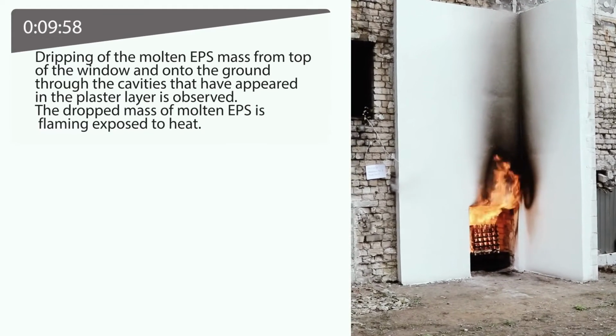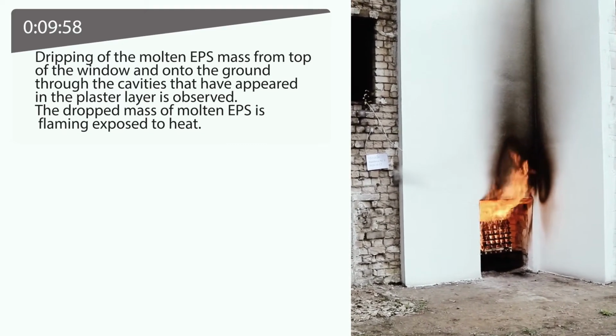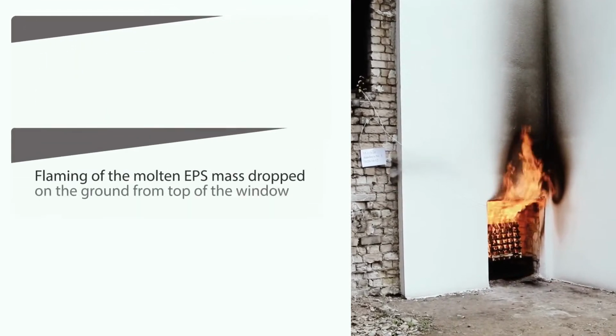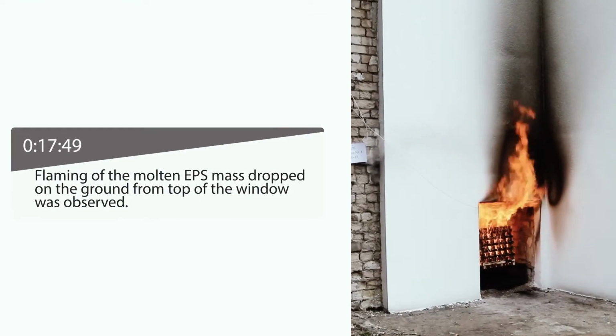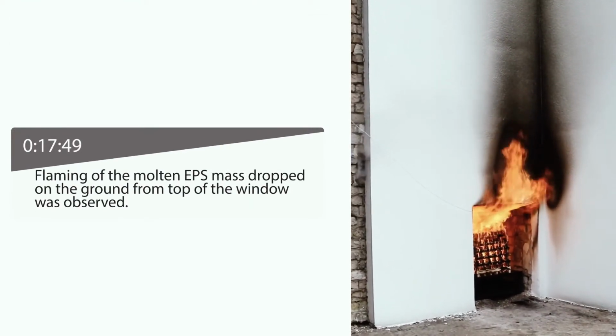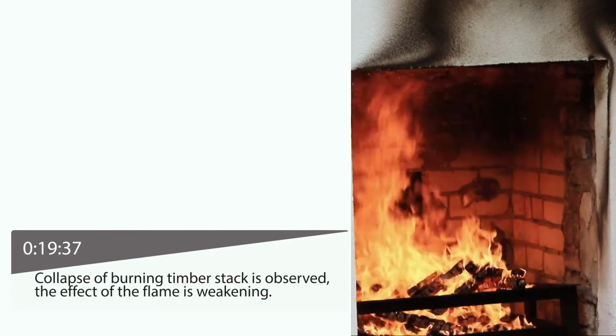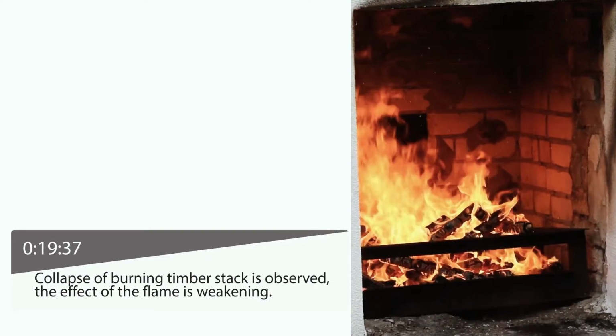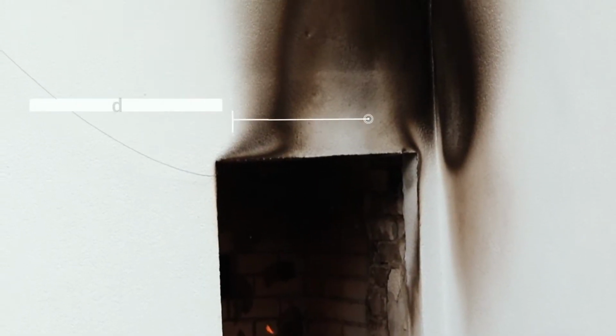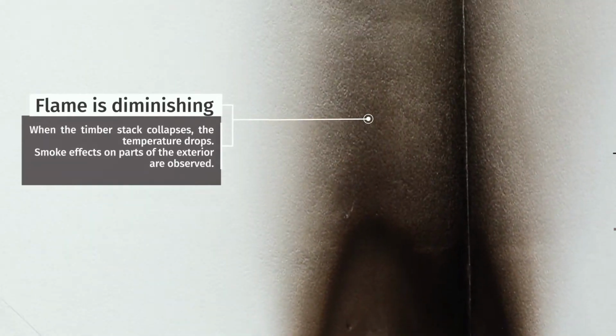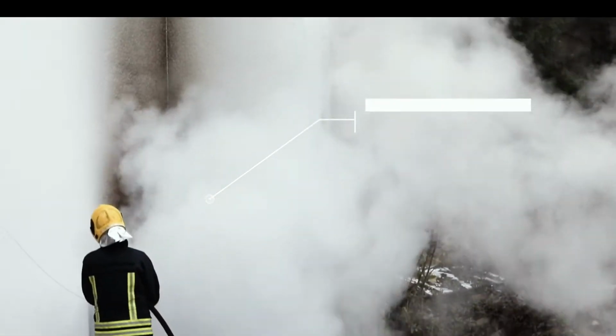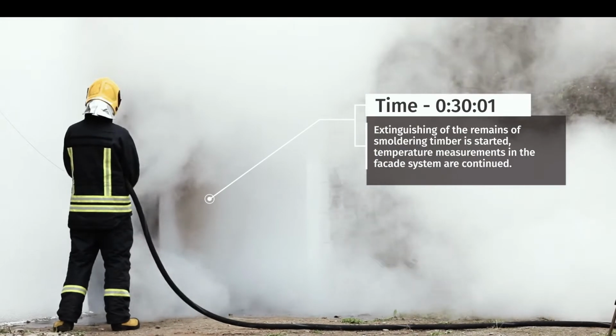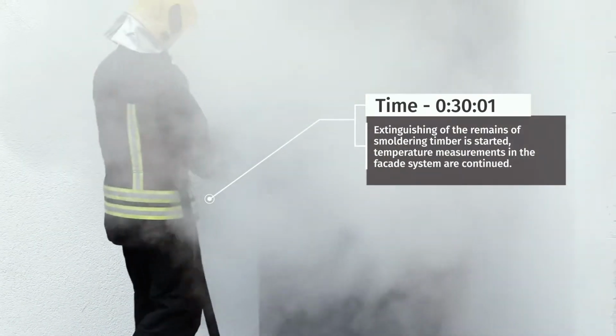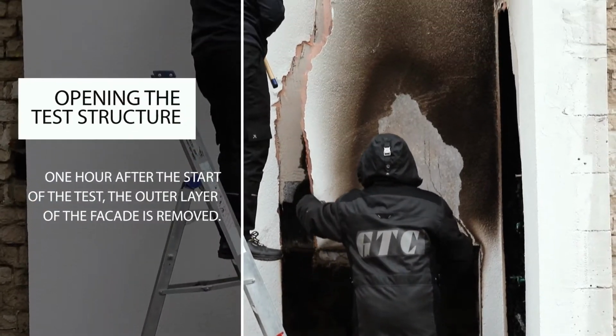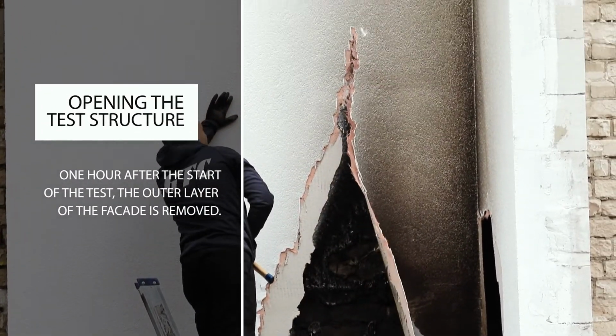Almost 10 minutes later, dropping of molten EPS from the top of the window is observed. After more than 17 minutes, flaming of the dissolved mass of EPS is observed. After 19 minutes, the collapse of the burning timber stack is observed. When the timber stack collapses, the temperature drops. After 30 minutes, extinguishing of the remains of timber is started. Temperature measurement is continued. 1 hour after the start of the test, the outer layer of the facade is removed.